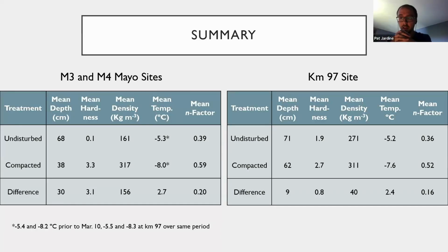So to summarize the last 5 pages of full graphs that I've shown you, here are the average values for the undisturbed and compacted plots over the duration of the winter. Snow depth was 30 centimeters lower in Mayo, as opposed to only 9 centimeters at Dempster. Hardness was 3.1 compared to 0.8, and density 156 compared to 40. In contrast, the difference in ground surface temperatures and N factors was only slightly larger at the Mayo sites.